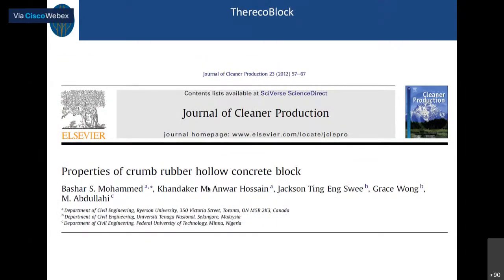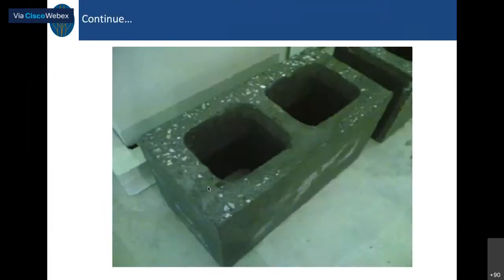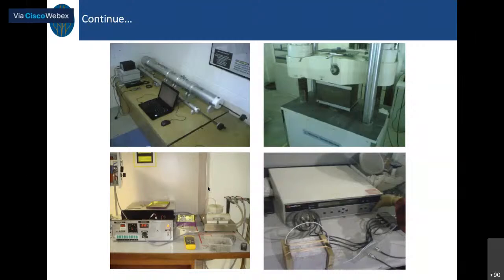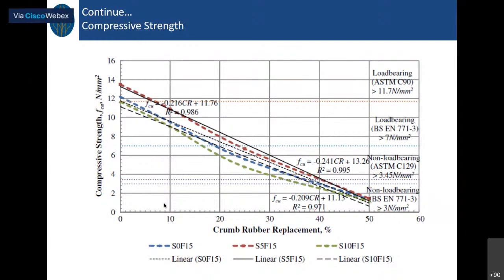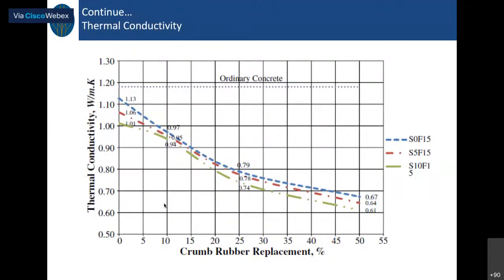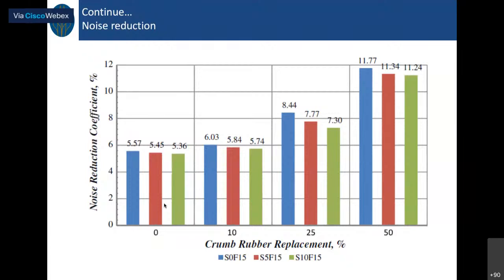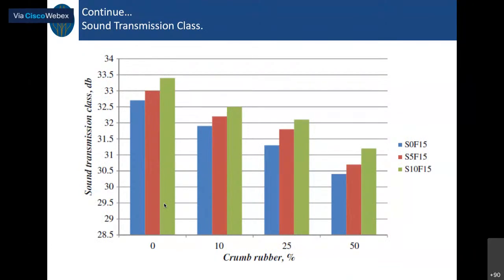Then we also developed this crumb rubber hollow concrete block. This block we have tested, and we find it is a very interesting block. There are many improved physical properties, such as soundproofing, low thermal conductivity, high electrical resistivity, and so on. It is load bearing and can be used as a load-bearing brick. The thermal conductivity decreases, which leads to energy savings. And you also see that the noise reduction increases and the sound transmission decreases.